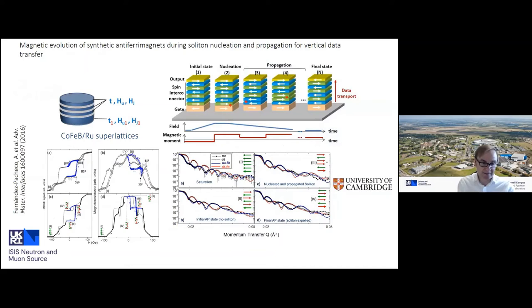Now, we're all familiar with microelectronics, but we're very familiar with 2D planar structures. So if you think about your chip or your storage in a computer, it's on two dimensions. But of course, if you can go in three dimensions, then you have potential to massively increase the storage density and so on and so forth. And so this is an example whereby you can create these little nanoscale structures. So these layers, in this case, are an alloy of cobalt, iron, and boron, a few nanometers thick, separated with a very thin spacer layer, in this case, ruthenium.